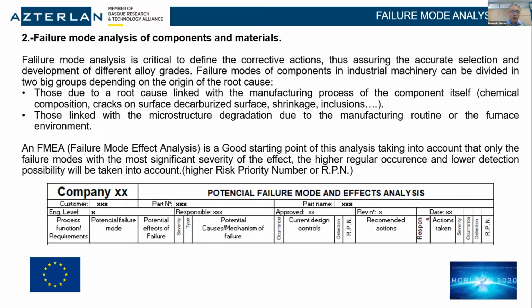For example, those due to a root cause linked with the manufacturing process of the component, mainly linked with bad chemical composition, cracks on surface, for example, decarburized surface, shrinkage, inclusions, defects generated during the manufacturing process. And those linked with the microstructure degradation due to the manufacturing routine or the furnace environment. As you know, if you come from the industry, the failure mode effect analysis is the starting point, taking into account that only the failure modes with the most significant severity of the effect, the higher level of occurrence and lower detection possibility are taken into account currently in these components.